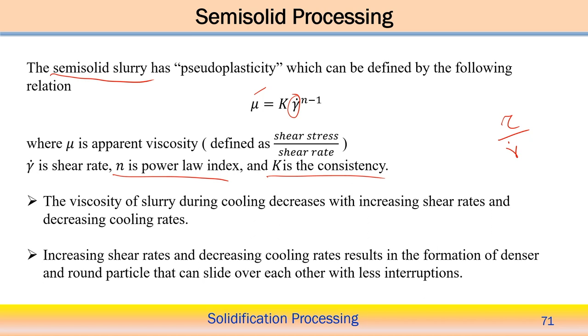Now, if it is completely solidified, then there is no viscosity in this case, but it gradually transfers from high viscosity to low viscosity during the semi-solid processing. So, the viscosity of the slurry during the cooling phases actually decreases with increasing the shear rate and decreasing the cooling rate. So, increasing the shear rate and decreasing the cooling rate, the viscosity of the slurry gradually decreases. This is the typical property of a semi-solid processed material.